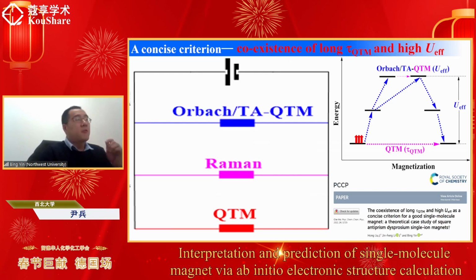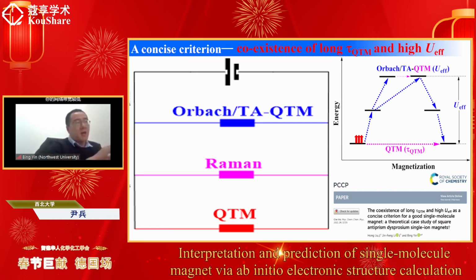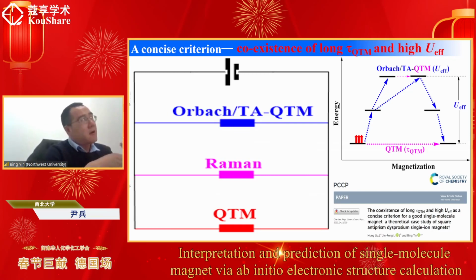So we propose a simple but comprehensive criterion for a good single molecule magnet, that is the coexistence of long tau QTM and high Ueff. Because if you have long tau QTM, that means the QTM relaxation will be slow. And if you have a high energy barrier Ueff, that means the thermally activated relaxation will be slow. So if all the possible pathways of relaxation are slow, the total relaxation will be slow. If the total magnetic relaxation is slow, the performance of the single molecule magnet will be better.